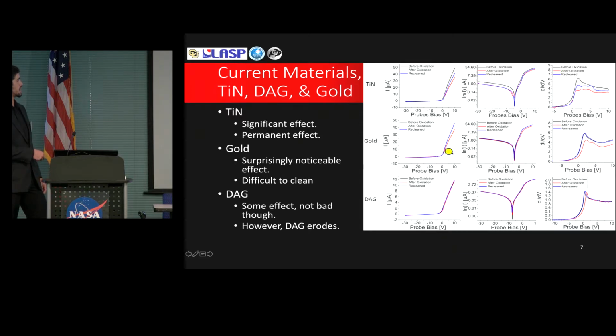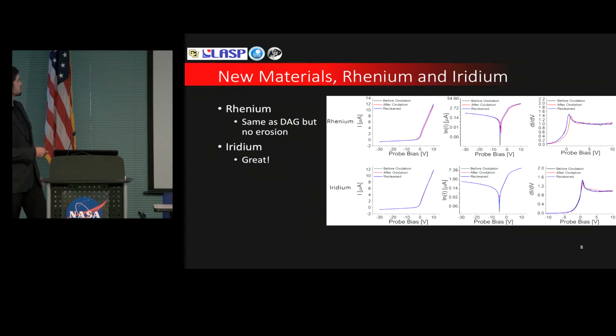Gold did have an effect after oxidation, more so than you would expect from the conventional thinking that gold is inert. And then DAG showed very little change before and after oxidation, but again has the issue of eroding when it's in an oxygen plasma. Then of the new coating materials, Rhenium showed pretty much the same response as the DAG, but the Rhenium has the benefit that it doesn't have a lifetime; it doesn't erode over time. And Iridium, frankly, did great.